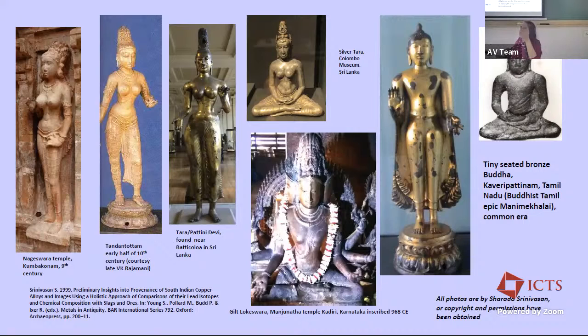And in fact, the trace elements didn't seem to fit that well with the Sri Lankan examples. And you also find that the Sri Lankan bronzes quite often have quite a significant trace of iron, which I never see in the South Indian examples. Although you do have a very important copper magnetite ore deposit in Sri Lanka, it seems to me at least that the iron traces being very low in the South Indian examples suggest different sources. And there is the possibility that this had some connection with the Tamil region, and you can also see that in the modeling.